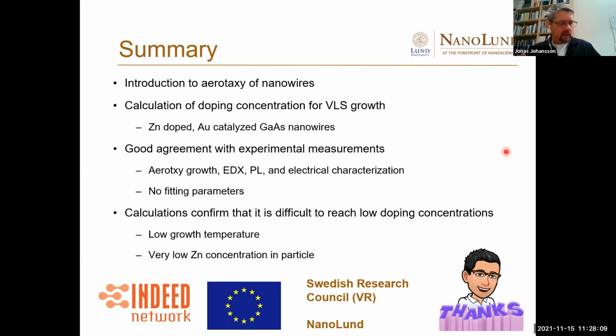So with that, I would like to sum up. So I have introduced aerotaxy as a method, and how to grow nanowires using aerotaxy. And I have shown how to calculate doping concentrations for vapor, liquid, solid growth, and applied it to zinc-doped gold catalyzed gallium arsenide wires, and good, or at least reasonable, agreement with experiments.